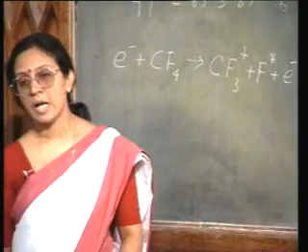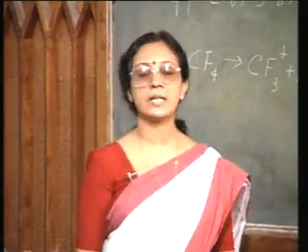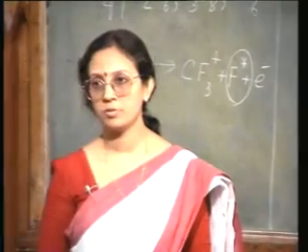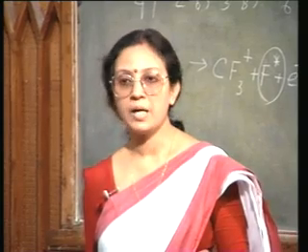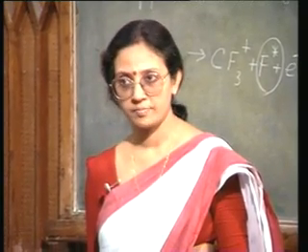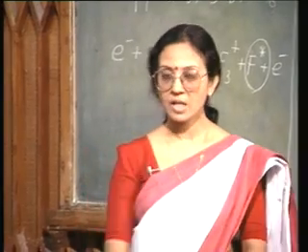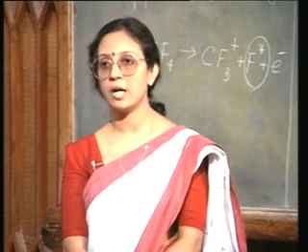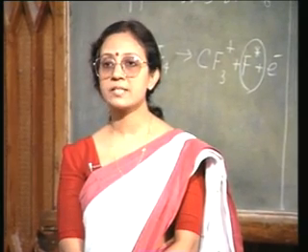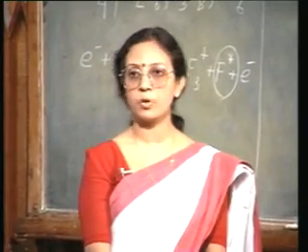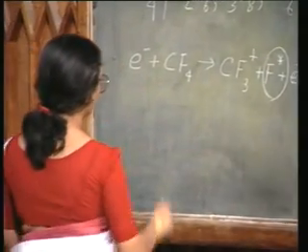Now, for silicon etching, this is the most important item. Silicon is etched by this free F star. This is the primary active species which is going to etch silicon. And how does it etch silicon? It reacts with the surface atoms of silicon and it forms a volatile product, SiF4.